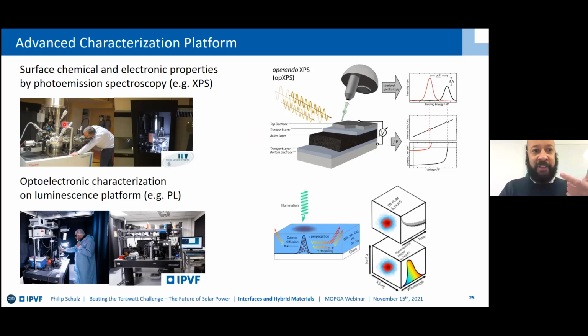It is small samples for which you probe the internal chemistry and electronic properties, either here with surface chemical and electronic characterization techniques, first and foremost photoemission spectroscopy or XPS, that we do mostly with our partners at the Institut Lavoisier de Versailles, or by optoelectronic characterization on a luminescence platform, for instance, photoluminescence. And here you see a small part of the PL capacities at IPVF.